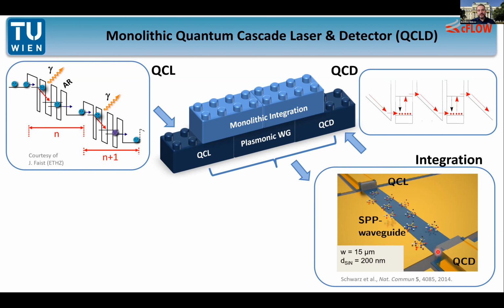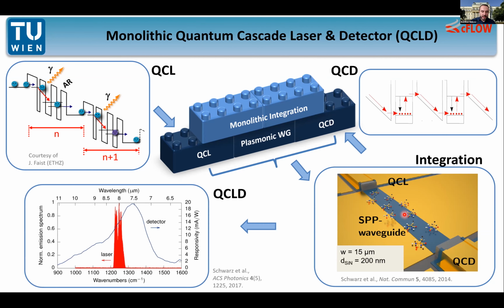To have this very efficient and to guide the light from one side to the other, we implement our plasmonic waveguide here. Because, as we said, we can couple the light to the surface and guide it nicely towards the detector, while a significant amount of the light is guided outside. Around 95, 96% in this configuration are guided outside. Here we use, by the way, not germanium, but silicon nitride on the surface for specific reasons of this experiment. So we could use this for a nice sensing experiment.